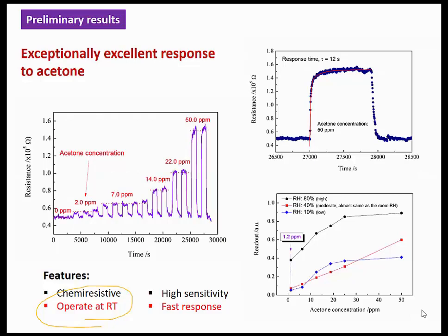And for the sensitivity, we can show the detection at different relative humidity, and we can see that even when the humidity is very high, the sensor performance is still very good. So we developed a material-based sensor with a good chemiresistive response that can operate at room temperature, with high sensitivity, down to 1.2 parts per million so far, and a fast response within 1 minute.